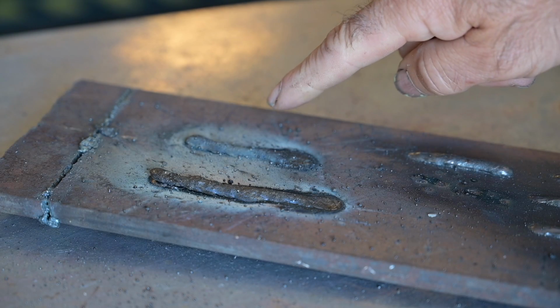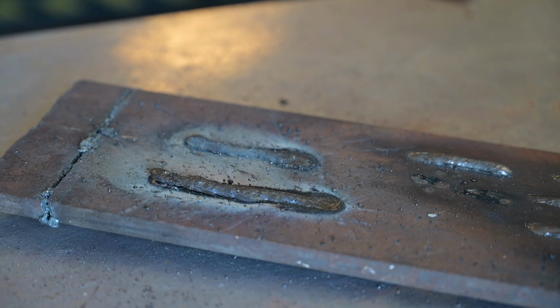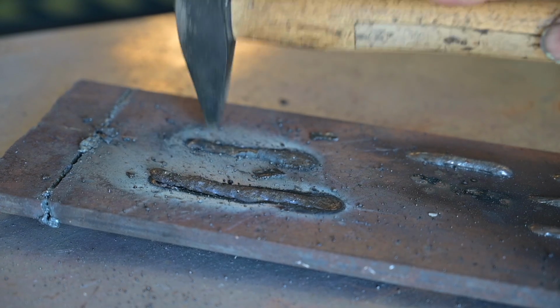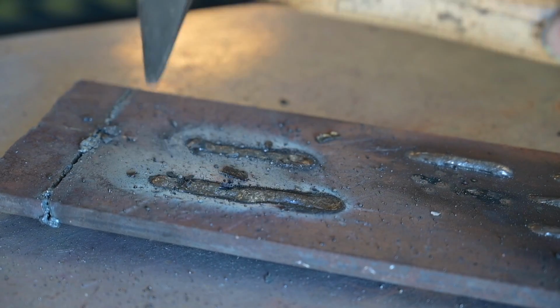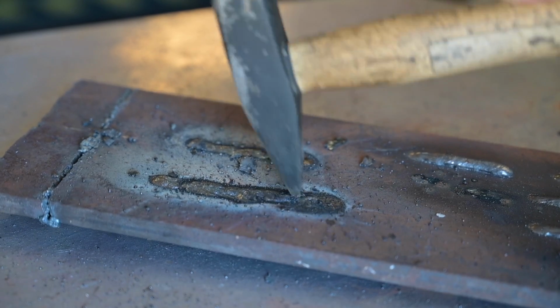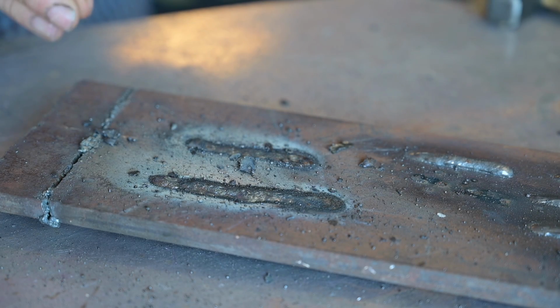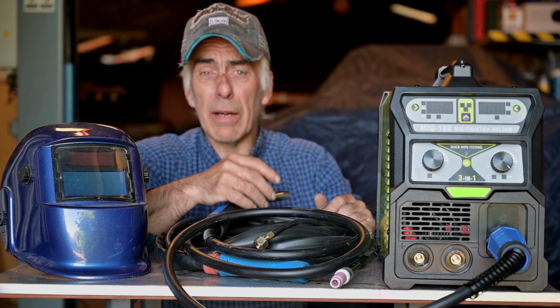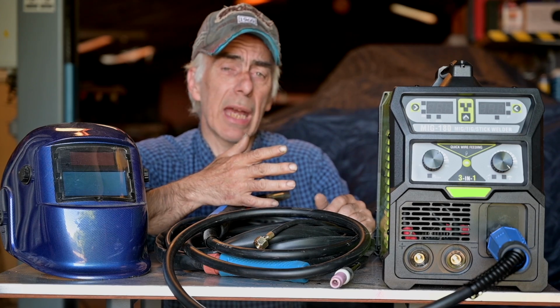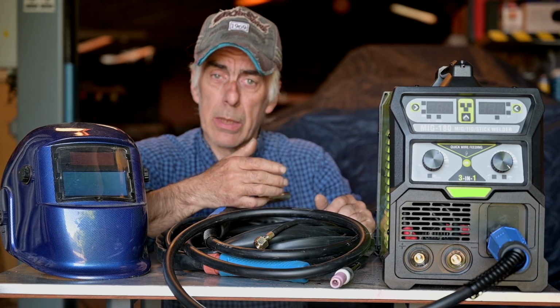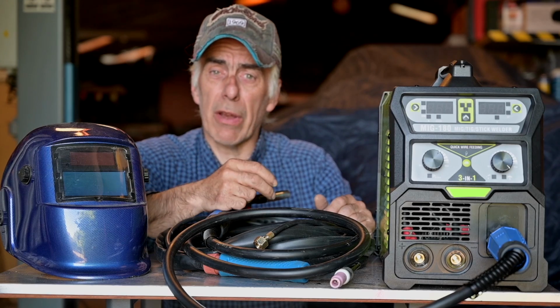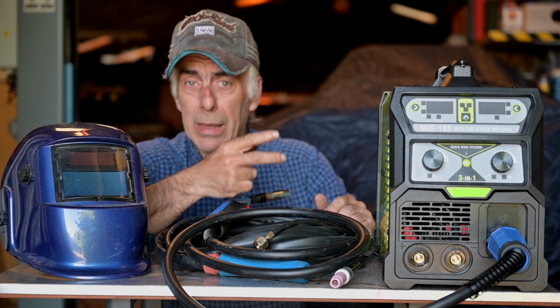Of the 90 amps weld and the 160 amps weld, so let's knock off the slack on that. So I've been welding at 90 amps, and I also welded at 160 amps, which is the maximum on this welder. So that all worked. I know the welds are not looking that perfect, but that's just me. But overall, I think this is working fairly well. My final conclusion on this welder is that we actually have 3 welders in one. We got stick, TIG and MIG. So that's a very positive thing. So it's a very versatile welder, I would say.